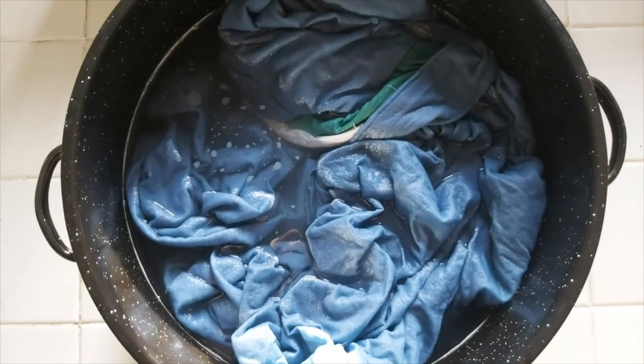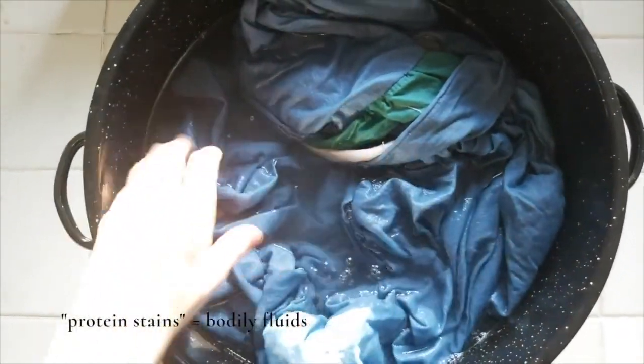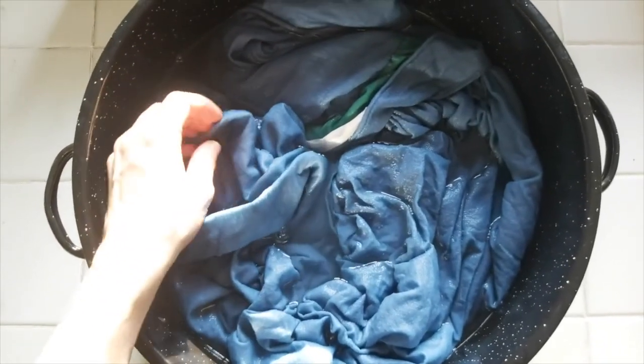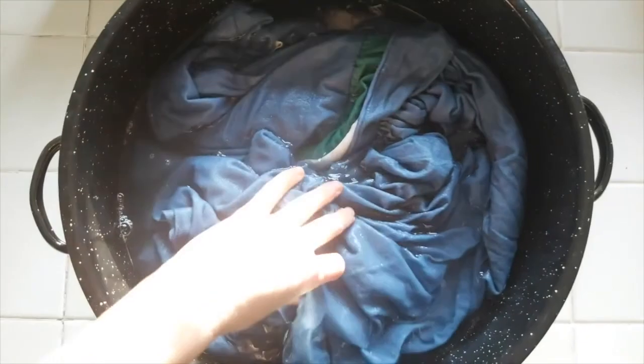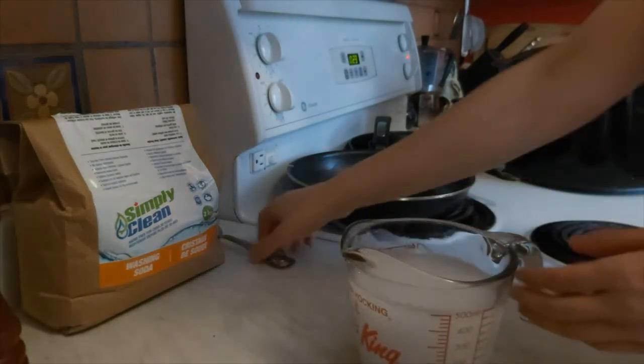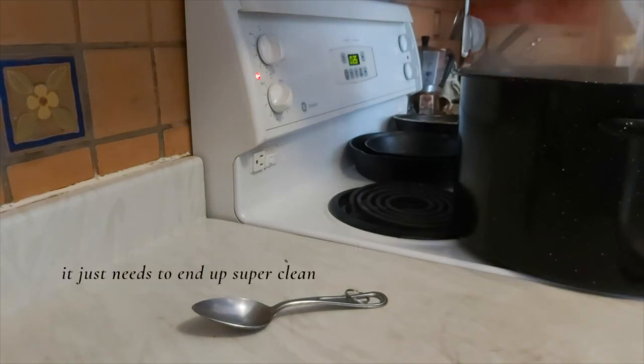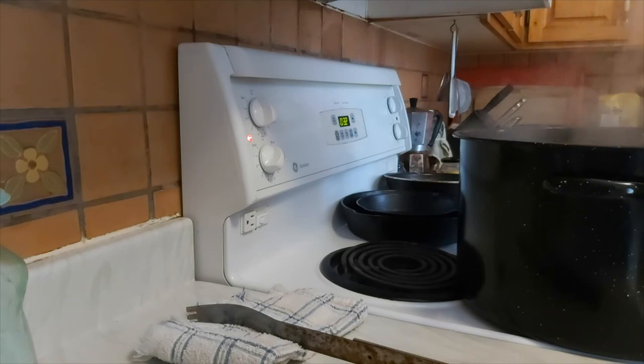To get ready to scour my fabric, first I'm hand washing it. The cotton flannel I used for this dress used to actually be a bed sheet — I just got it at the thrift store so it's probably covered in invisible protein stains and other stains. I'm worried about those coming through in the dyeing process. Sometimes dyes adhere more to proteins than to the cellulose of the cotton, but that's less of a problem with tannin dyes. I'm still going to try really hard to make sure the fabric is clean and stays evenly treated throughout the process. The dress is now rinsing in the sink and I'm preparing my scouring bath — a pot of boiling water with two scoops of washing soda and a little bit of dish soap. This will foam up so I'm giving it a stir and letting it settle before I put the dress in.